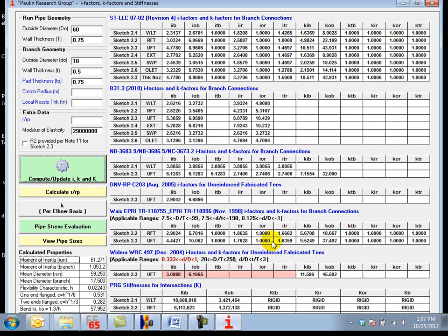B31.3 in this case is simply overestimating the stress by about 10 times. K factors for this branch connection would be a number of around 43. This agrees fairly well with the 45 from WRC 497. B31.3, of course, provides K factors of 1 for all branch connection components. So this is the equivalent of leaving out 43 diameters of straight pipe at this branch connection.